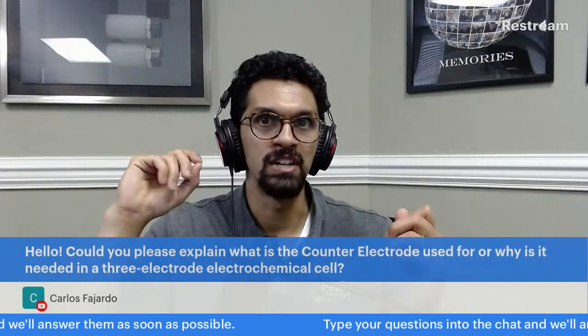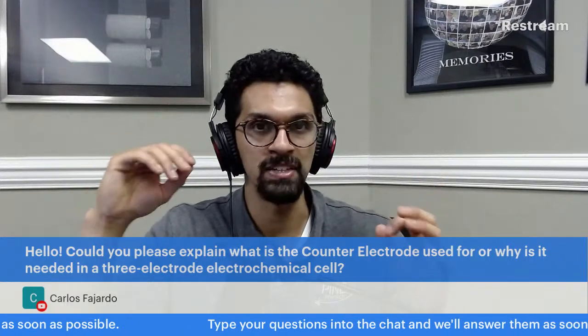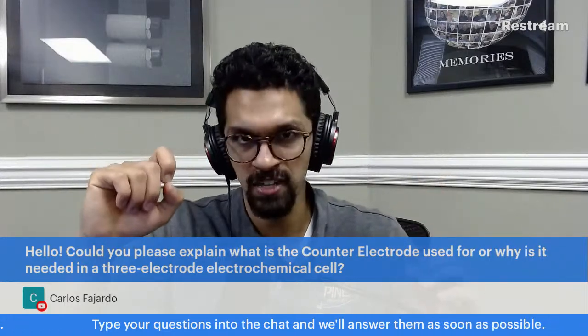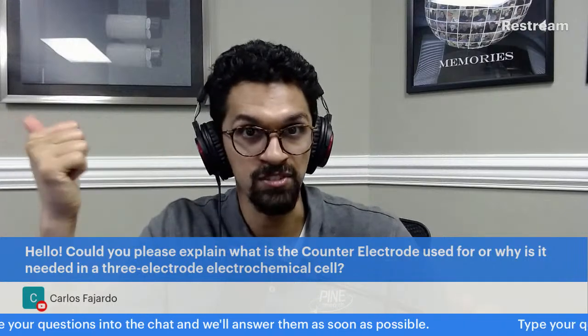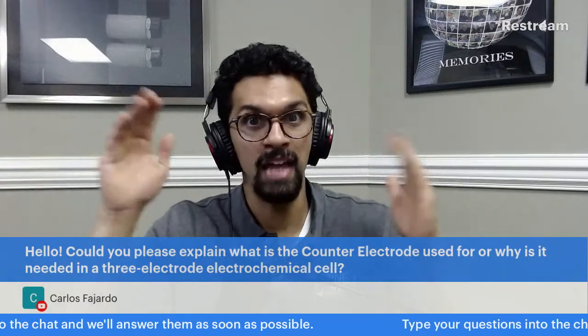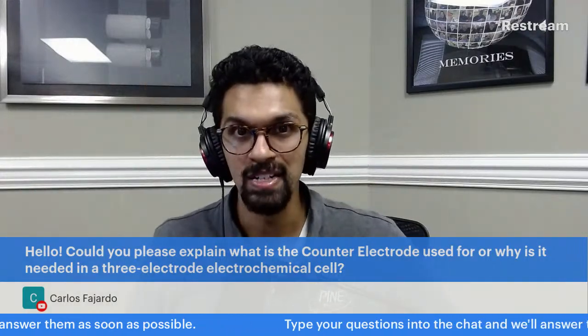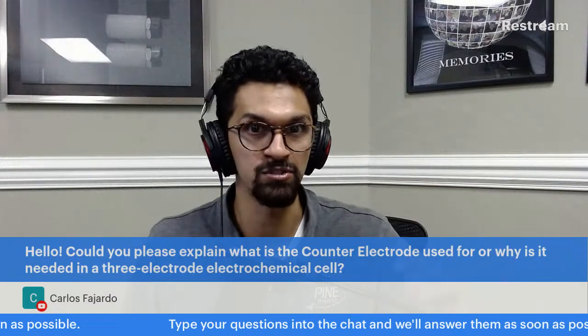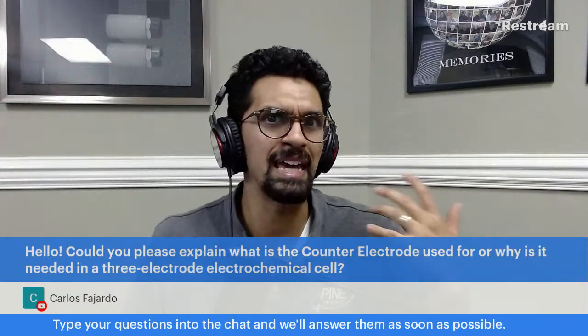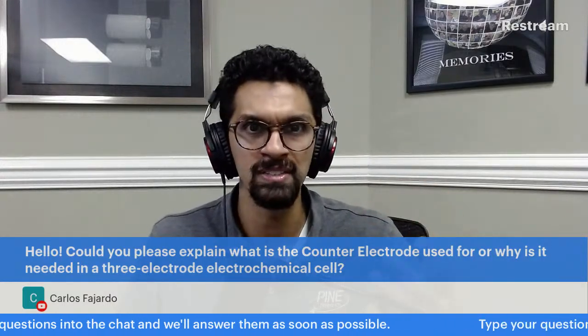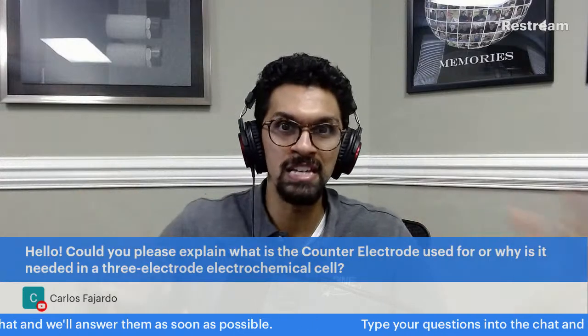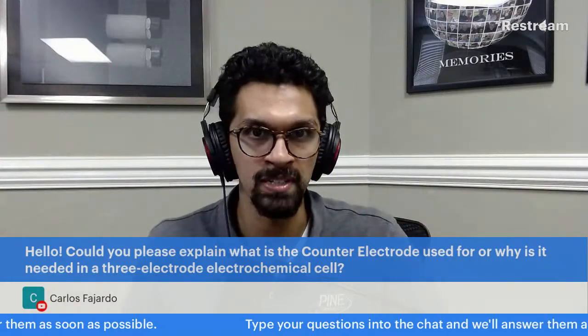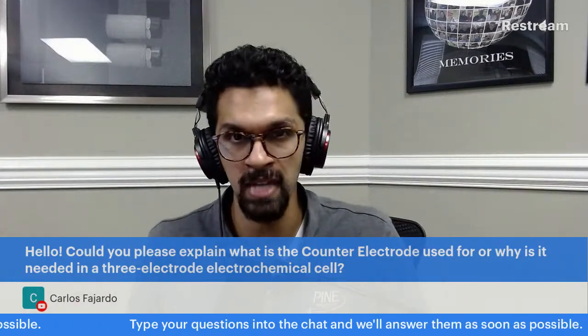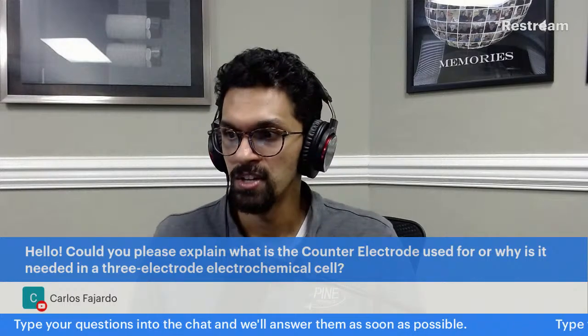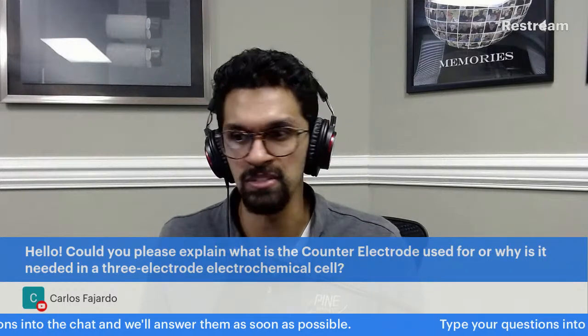So if you don't have an adequate counter electrode, and this can happen, your working electrode reaction is not going to occur. Not because the working electrode is bad, but because the counter electrode is either too small or can't actually react or generate the current that needs to be equal and opposite to that of the working electrode, or the charge that needs to be equal and opposite to the working electrode. So that is what the counter electrode is used for.